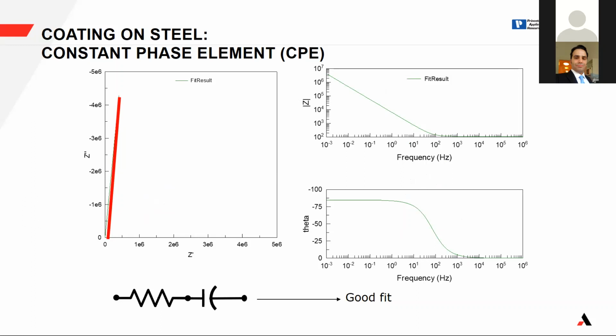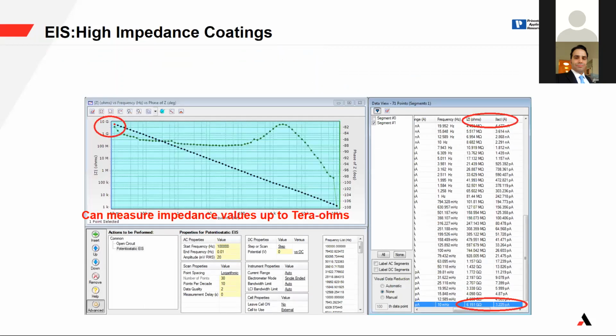So when you see something that is not a perfect semicircle, you have to think, hey, that one is a constant phase element. That one is not a pure semicircle. I'm sorry to tell you, but 99% of the time, you have a constant phase element. Forget about a pure capacitor. Leave it to the theory, leave it to the electronics people, you have a constant phase element. I'm sorry to give you this reality. So you see, you can go to very, very high impedance. This one is 1 gigaohm. Sometimes we also have specific instruments that go to 100 gigaohm. So you can measure very high impedance if you like, but keep in mind this situation.